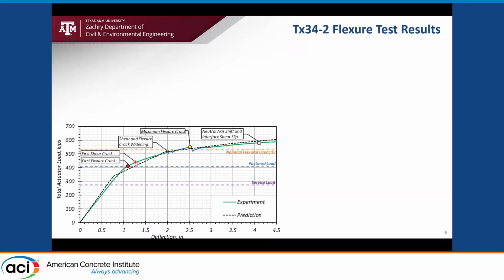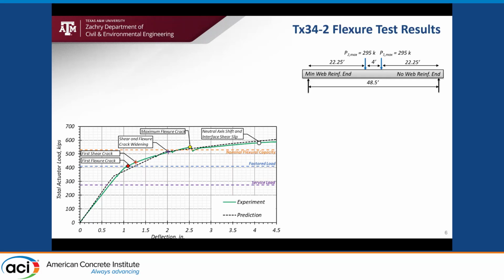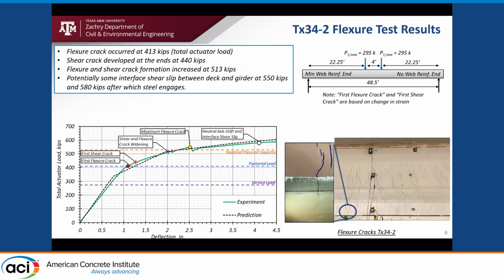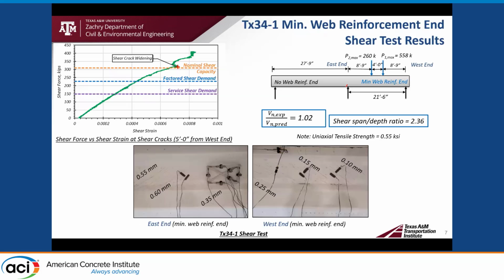The second specimen had better tensile strength of 0.625 KSI, and we had higher shear capacity due to harped tendons and more prestressing. Therefore, we did not run into any issue of premature shear crack with this specimen. We conducted the 4-point bending test until we got the flexure failure under one of the actuators, and we got a higher capacity of 6,400 kip-feet for this test.